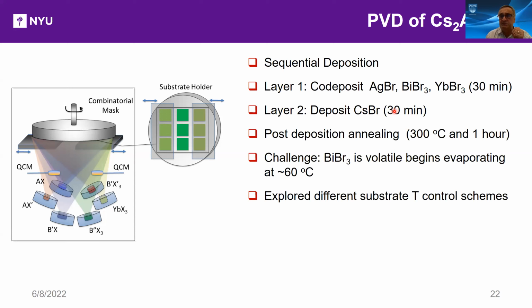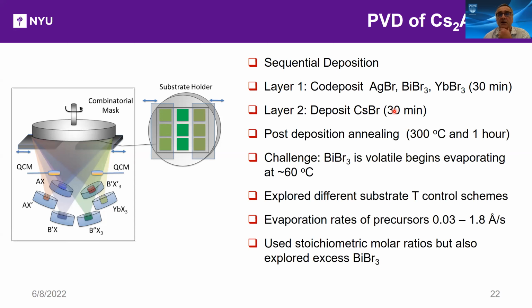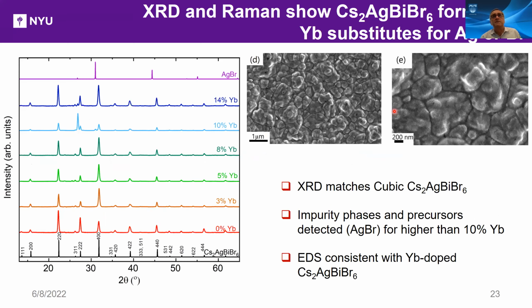So for this reason, we explored different substrate control schemes. The evaporation rates of precursors range, depending on what we want to do, just to give you a feel, from 0.03 for ytterbium bromide, where we're trying to dope at low concentrations, to 1.8 angstroms per second for excess bismuth bromide. We typically use stoichiometric molar ratios, but we explored excess bismuth bromide with this compound as well. And film thicknesses, we're looking at a few hundred nanometers, and all the ones that I'm going to talk about are about 500 nanometers.